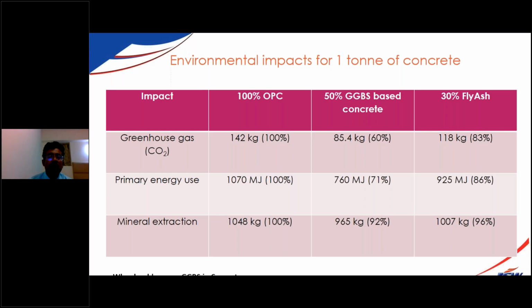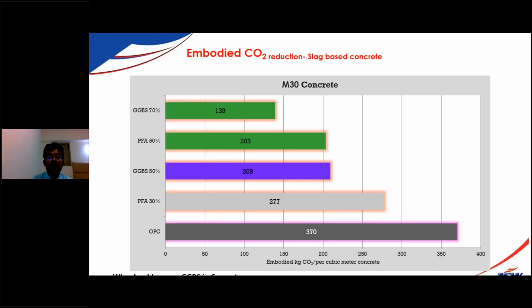So look at the greenhouse gas emission per ton of concrete. These are the numbers which have been calculated. This clearly shows the GGBS concretes are superior compared to the pure OPC concretes, or even superior to the fly ash mixes. So with a higher replacement of 70%, for M30 grade concrete, how much CO2 reduction you can do? It is shown here.